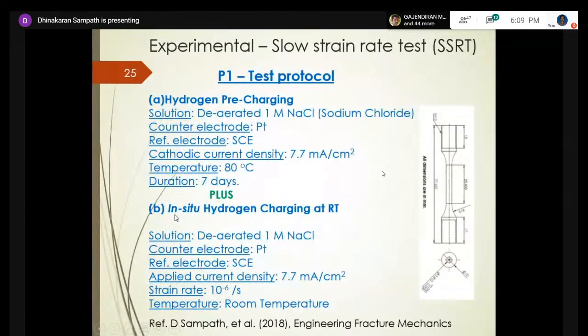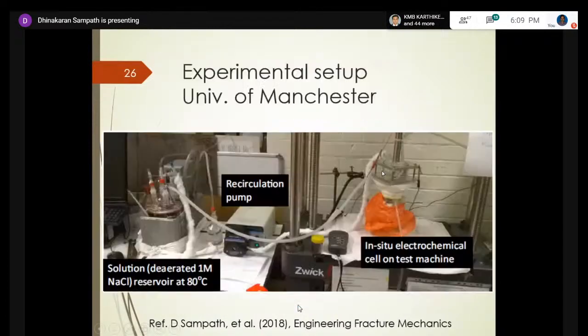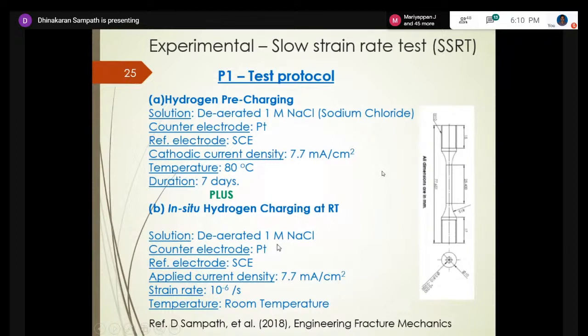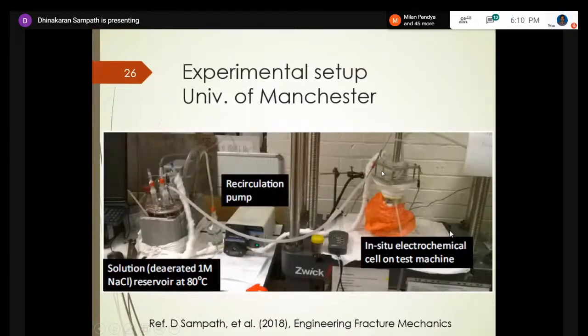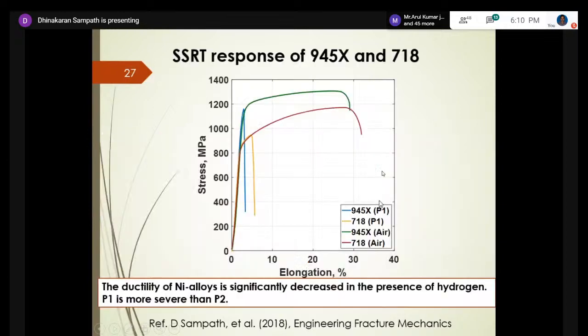That's the reason why they think that these are good materials for hydrogen service, but still they have their own problems. And then we did the in situ hydrogen charging and conducted the tensile test, that means while conducting the slow strain rate tensile test, simultaneously charging the sample with hydrogen. So this is the experimental setup. We have this pull rod and mount the electrochemical chamber around the subsize slow strain rate tensile specimen. And we have the recirculation pump to provide deaerated sodium chloride solution. Here we have a three electrode system to effect hydrogen generation.